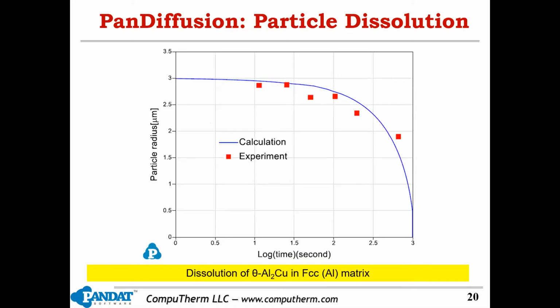And with a diffusion module, we can also do a homogenization simulation. In this case, we simulate how the Al2Cu particles dissolve in the aluminum matrix. So this is the particle size, y-axis, and this is the time. So at the beginning, we have very big particles, and then gradually they dissolve with time. Okay.